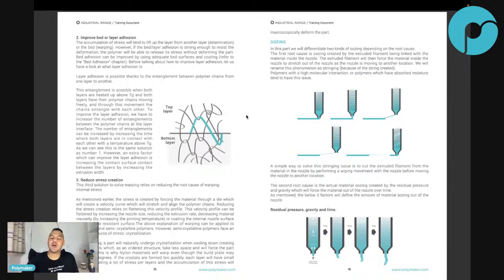So what is our warp-free technology? Why can you print our nylon so easily? And why can you print our semi-crystalline so easily? Because we found a way to control that crystallization rate. When you print with our nylon, it's not going to crystallize as fast. That's why we also recommend to anneal the part afterwards, because maybe it didn't finish the full crystallization during your printing process. So you can finish that crystallization in the oven.